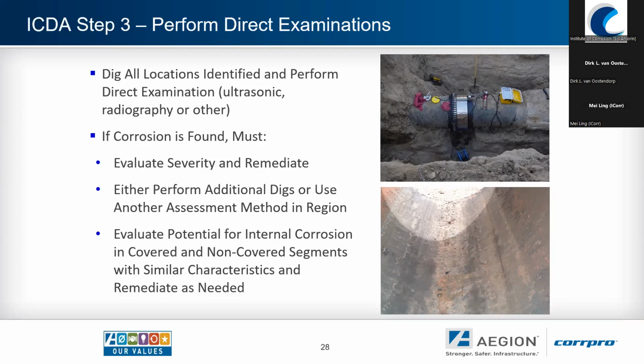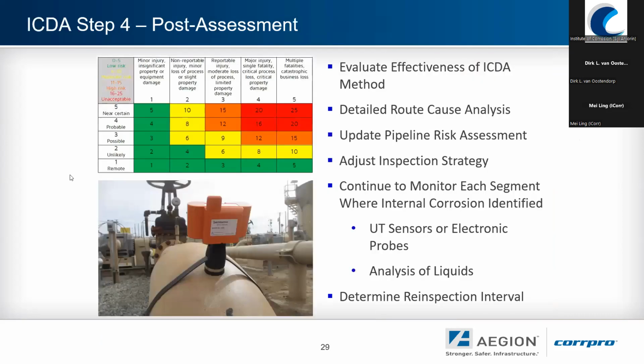This is where ICDA determined that there was water sitting in there for about 3,000 to 4,000 hours before it would actually move through. So there was a constant flow, but there was also water trapped in there. So good confirmation for the technique being functional and working.